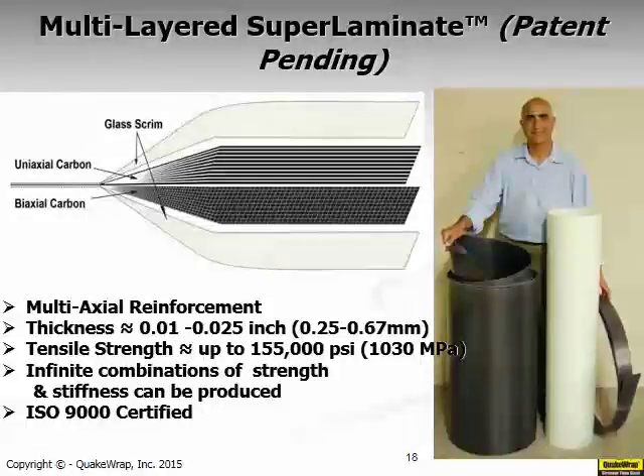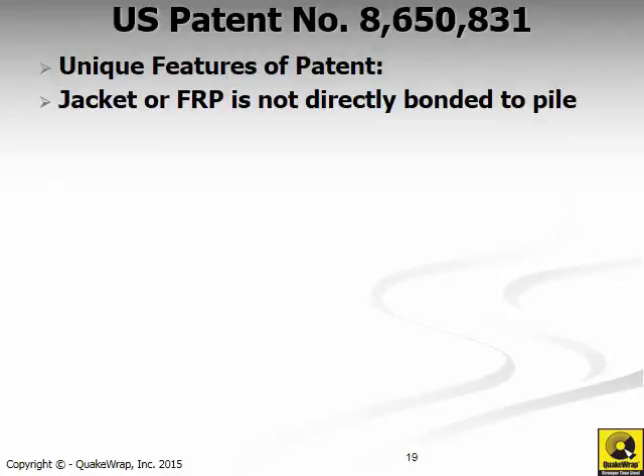So the system consists of a manufacturing technique that we have developed where we can put one or more layers of fabrics together and apply the resin and the heat and pressure to these. And out of these fabrics, we manufacture some thin laminates, as you can see on that I'm holding. These laminates typically come in rolls that are 4 feet wide, and their thickness is very small, from 1/100 of an inch to 25 thousandths of an inch, but they have very high tensile strength, as much as over 150,000 psi. And as you'll see now, they can be very useful, for example, in repair of columns and so on.